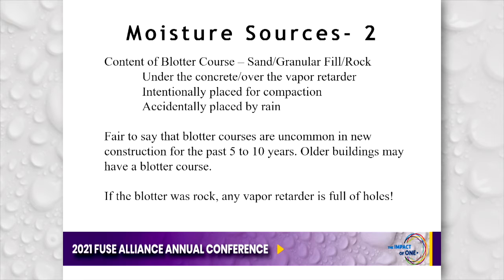So if we look at moisture source 2, this is what I'm going to call the content of a blotter course. Now, blotter courses aren't used as much today as they were in the past, but they were typically sand or granular fill or rock. This is the layer between the concrete and the vapor retarder. So under the concrete but over the vapor retarder, any moisture in there may be intentionally placed because we can't place concrete on dry sand. We have to wet it to gain compaction, or it could be accidentally placed by rain.